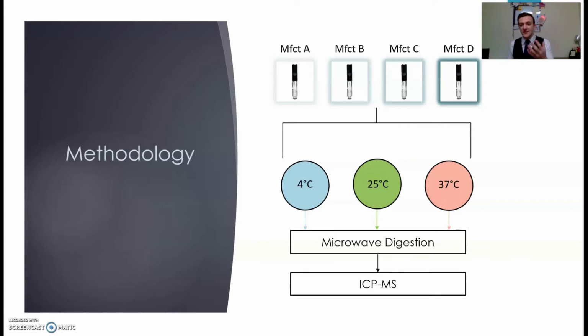I was able to obtain 90 cartridges from 4 different manufacturers for use in this 10-day study. Now, it's important to note that these were stock cartridges, meaning cartridges straight off the manufacturer floor that hadn't undergone any of the steps in the downstream production process where the cartridges are stocked with cannabis concentrate. Thus, any nickel contamination that we potentially found would be a direct result of either the manufacturing process or the construction of the cartridges themselves, with nickel being introduced via metal leaching.